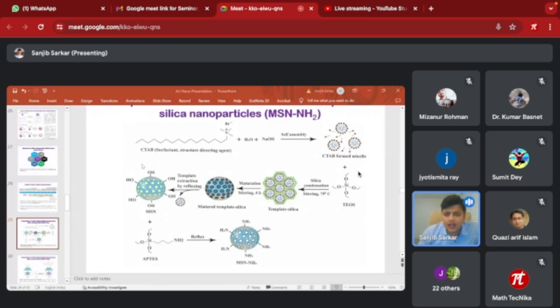with the phenylboronic acid, these bonds are broken due to the interaction with the 1,2 diol of the glucose molecule, and this glucose molecule joins here, and the dextran molecule is released from here. I didn't show the dextran molecule here, but the dextran molecule was released from the surface of the nanoparticle, and the glucose molecule binds to the phenylboronic acid. And see here, this drug is coming out from the nanoparticle pore.